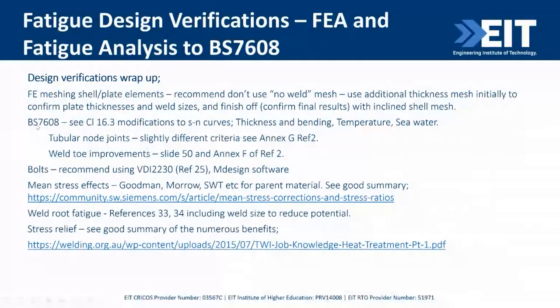shell mesh. There are corrections on the 7608 curves for thickness and bending and temperature and seawater. Tubular node joints are managed slightly differently, and weld toe improvement needs to be used if you're using that, in a couple of slides. I mean, you've got to be careful about weld toe improvements, because if it takes you a lot of time and effort and cost, then you're better off using a bit thicker plate and larger welds to get your fatigue resistance down.